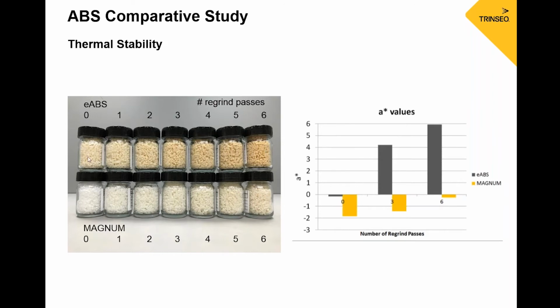What was interesting, as you can see visually, there is a greater change visually, and what that change is, is the redness and the A star values that we measured. This was more interesting because there was a much greater shift in that redness with the emulsion product versus the mass Magnum product. So with the mass product, it shifted less than 2 units more red. So with the A star value, the positive being red and the negative being green, it's shifting more red, the more positive that number becomes. So the emulsion product shifted a little more than almost 6 units more red.